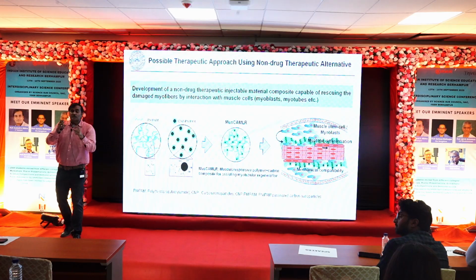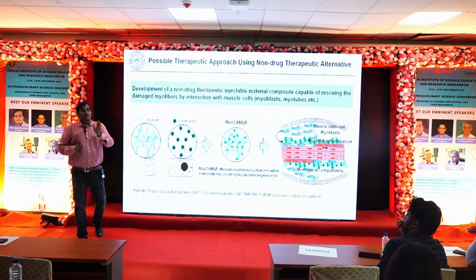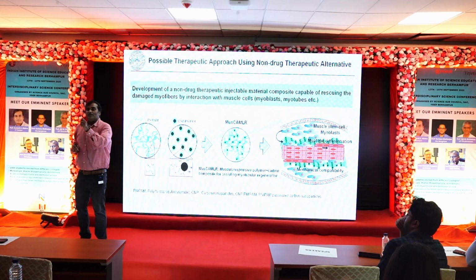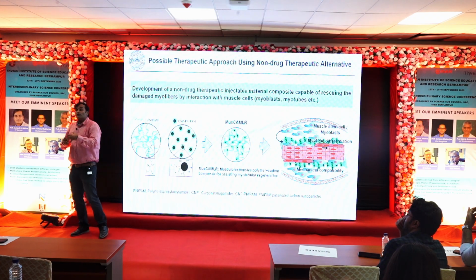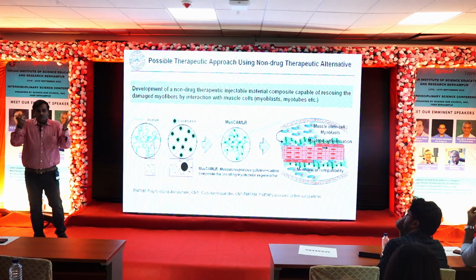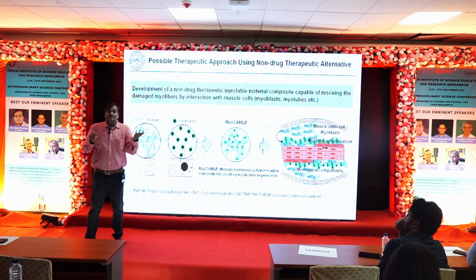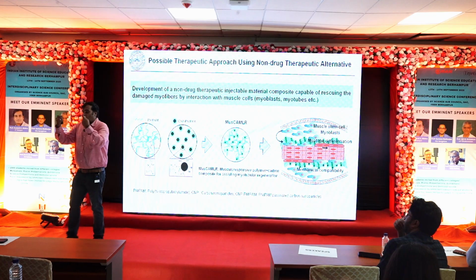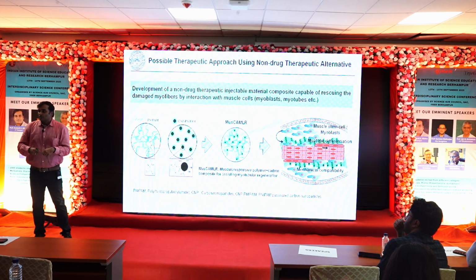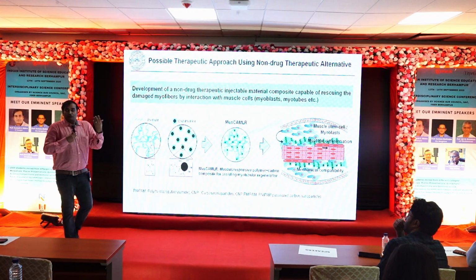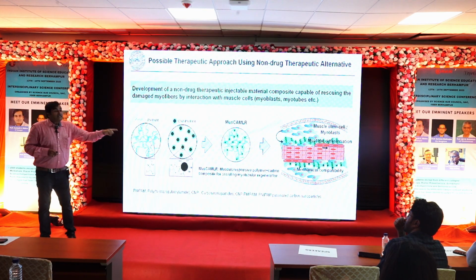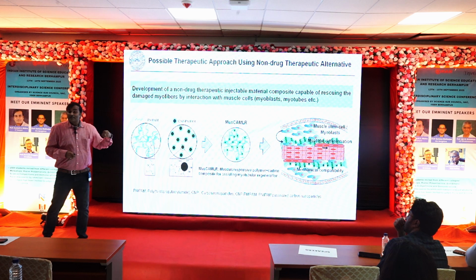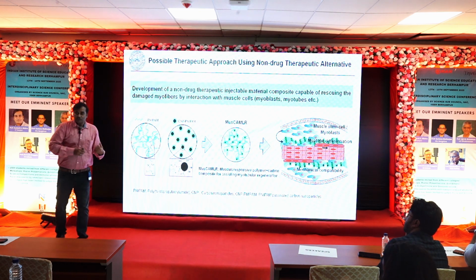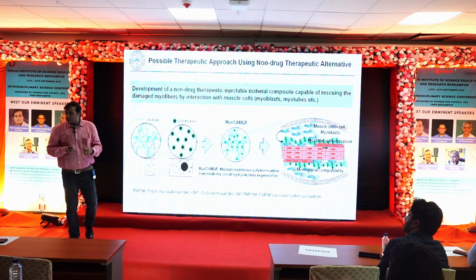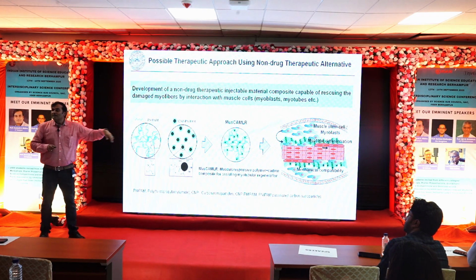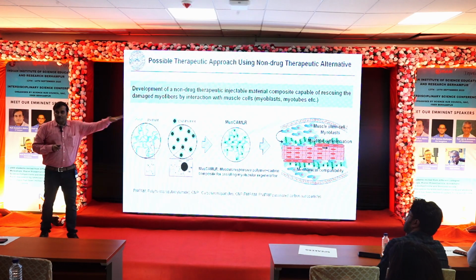If it is not matching, that's why it is slowing down. So in old age, muscle generation is reduced because you will find muscles are not that tight. In simpler terms, mechanical strength is gone. So one thing, muscle is lost, another, mechanical strength is lost, and that's why it is not able to do that kind of regeneration. Luckily, we found that our system which was generated is matching in mechanical strength, and that helped us design this injectable hydrogel material.